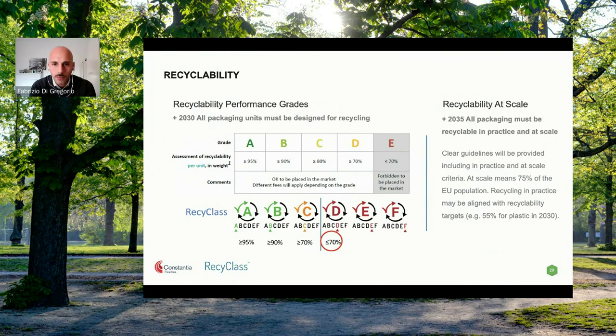If you look at the bottom of the slides, you can see that this is exactly what RecyClass is promoting. Since 2014, so 9 years ago, we started with RecyClass as a tool coming from the European plastic recyclers. And the logic was to promote recyclability not as a binary for plastic packaging, but with a class ranking from A to F, where A, B, and C are almost fully aligned with the proposal from the Commission. And in any case, from D to F in RecyClass, we recognize that packaging is downcycled and/or not compatible with recycling. And the limit of the D class by RecyClass is exactly the same threshold that the Commission is going to impose with the regulation.